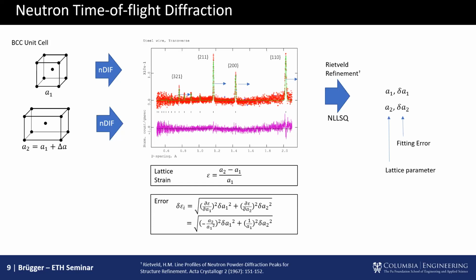Since we're doing an atomic measurement, we first have to understand the material and the multi-phase behavior of the material, to understand which phases have micro or nano strain behavior that can be mapped to the macro level. So in the case of steel, it's generally the BCC ferrite phase. If we measure the BCC ferrite phase, the body center cubic lattice parameter, then that maps essentially perfectly to your global strain.